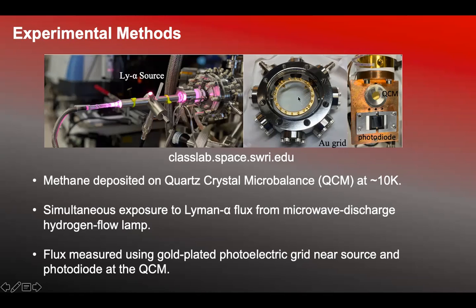As the methane is being deposited onto the QCM, at times a Lyman alpha light source, so that's this microwave-discharge hydrogen-flow lamp here, is beamed onto the deposit on the QCM, and you can actually measure the rate at which the deposition changes with this irradiation, etc. The flux of the Lyman alpha radiation is measured by this grid that you see here and this photodiode.